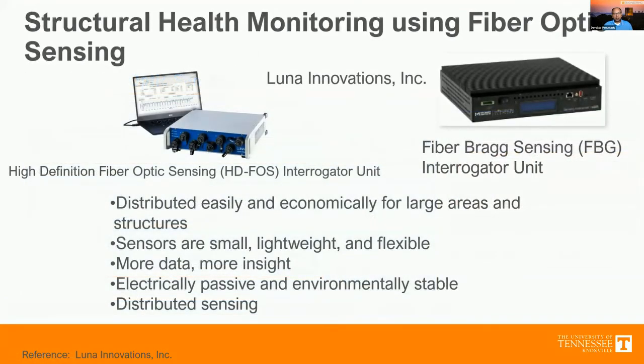There are 2 types of fiber optic sensors. The ones we just talked about are often abbreviated as High Definition Fiber Optic Sensing. These are distributed sensing. We also have the option to look at what are called fiber Bragg gratings, where we can have predetermined locations for Bragg sensing. And these come into play where we want a very, very high data acquisition rate. With these systems, we can measure spatially resolved strains up to 100 hertz over a 20-meter length of distributed fiber optic sensing, equivalent to 20 meters of strain gauges.